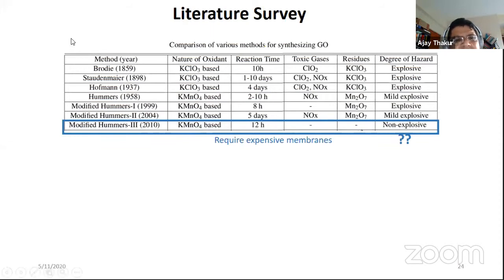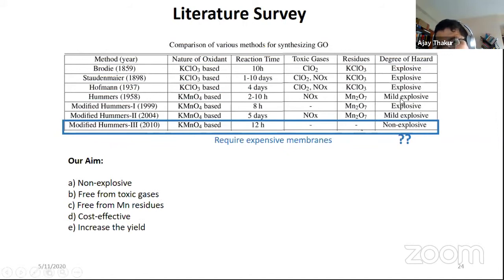And interestingly, just like the story of graphene, where a lot of researchers were aiming to make graphene-like materials or graphene for a long period of time, similarly, graphene oxide was not something which came suddenly after the discovery of graphene. Rather, a lot of groups were working as early as 1859. But one of the biggest problems with their method of synthesis was that the steps involved in the synthesis were highly explosive. So that really inhibited its use in industrial applications, because whenever we would like to make it for large scale applications, we have to make it in large amount, and then explosive nature of the reaction was a strict no-no.